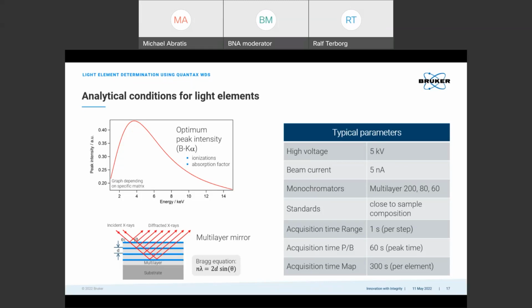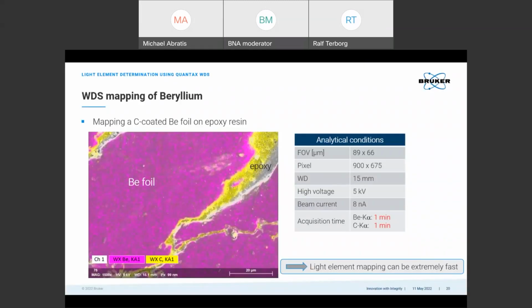On the right-hand side, we can see the quantum efficiency of an energy dispersive spectrometer equipped with the light element window. This is the efficiency, which is defined as the number of detected X-rays divided by the number of incoming X-rays. Here also again versus energy, and we can see that it is lower for low energies than for energies above 1 keV.